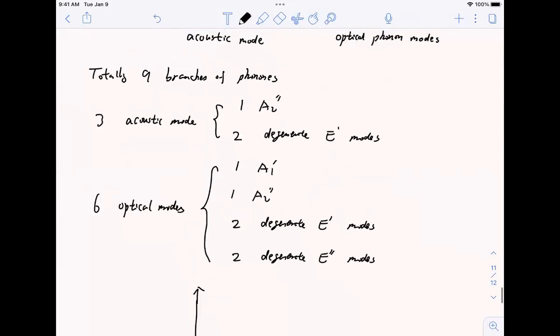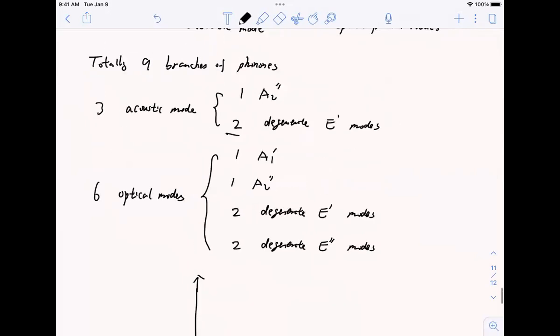Okay. So if you draw the diagram, using your common knowledge, you would be able to visualize what the phonon band structure looks like. First, you have 3 phonon modes. They all have zero frequency. However, 2 of them are degenerate due to symmetry. 1 is not. From the symmetry group, you know this is Z. This will be XY.